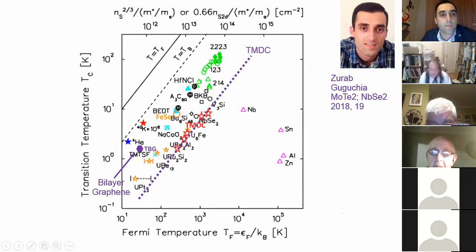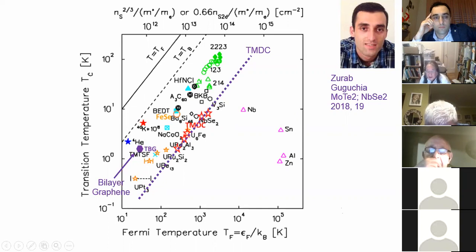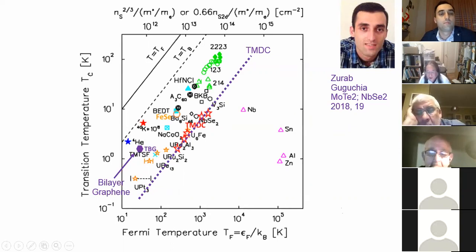Yeah, so oxygen content. Actually there are various ways to change the chemical composition, essentially doping charges. The initial doping was performed by lanthanum and strontium composition change in copper oxide. And lanthanum has a tendency to become 3 plus, and strontium has a tendency to become 2 plus. And so this ionic tendency is different, and so a slightly different composition would change the charge carrier numbers.